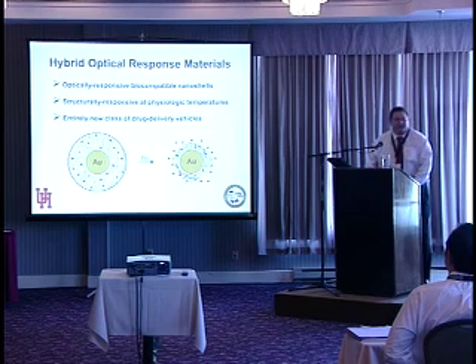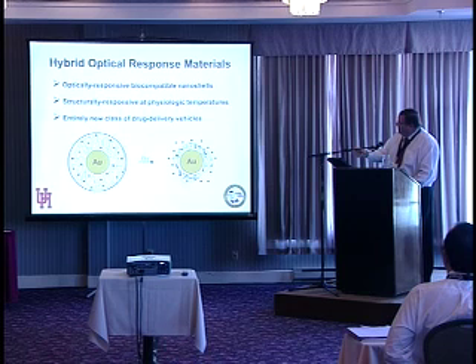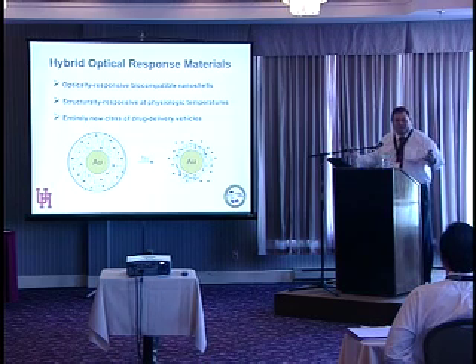So in this case, what we do is we take a metal nanoparticle and coat it with a thermally sensitive hydrogel polymer in which we can incorporate a drug molecule. So these little black dots are supposed to be the drug molecule. And if we apply our near-infrared laser, of course, the nanoshell particle will get hot, causing the hydrogel to collapse and release the drug. So in this case, we can imagine a dual therapy where we're doing drug release and heating at the same time.